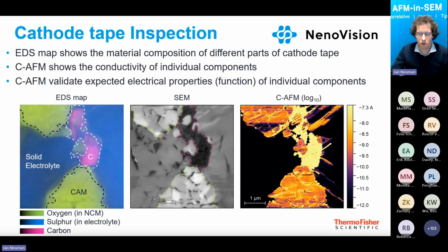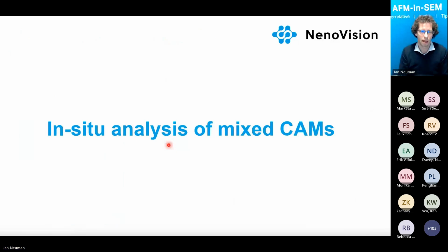Adding the measurements of conductivity and conductivity mapping, we directly confirm the proper function of each component, because the solid electrolyte is supposed to be very conductive for lithium ions, but should not be conductive for the electrons. We measure electric conductivity, and this is exactly what you see here. It's dark. We see the carbon, which is an additive, is highly conductive, as it's supposed to be. And you can also see the different contrast of cathode active materials. So you can validate that each component plays the role it's supposed to.